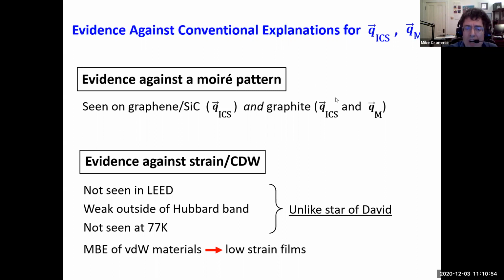So it doesn't work. But then you might think, well, in silicon carbide, you have all these weird reconstructions, you know, I forget what it's called, root 6 by root 6. You have some strange reconstructions between the graphene and the silicon carbide, which might cause it, but that's why we did graphite. Graphite does not have those weird reconstructions. And once again, we see the q ICS. So we think that this is strong evidence that it's not a Moire pattern.